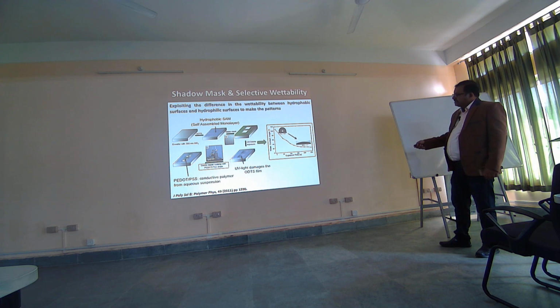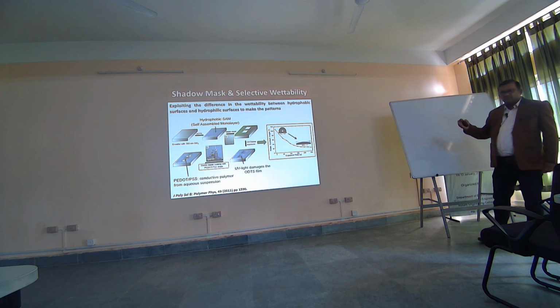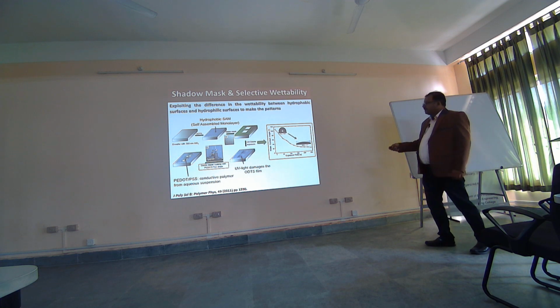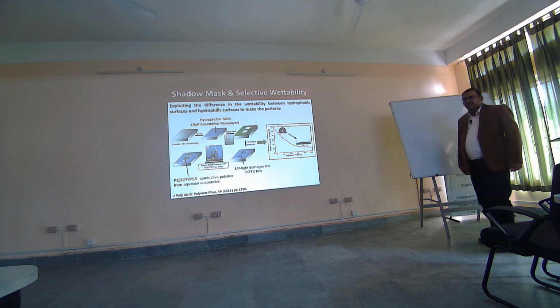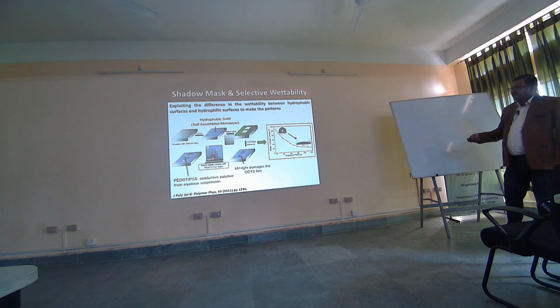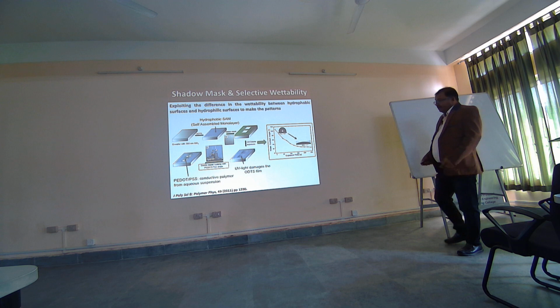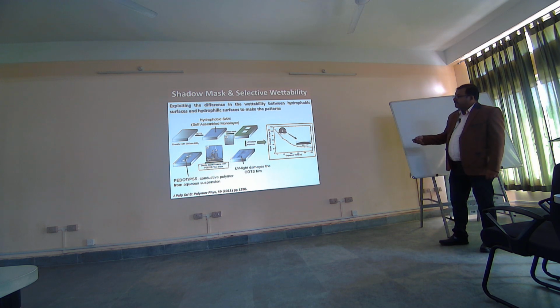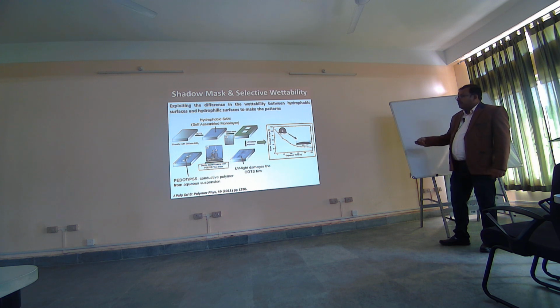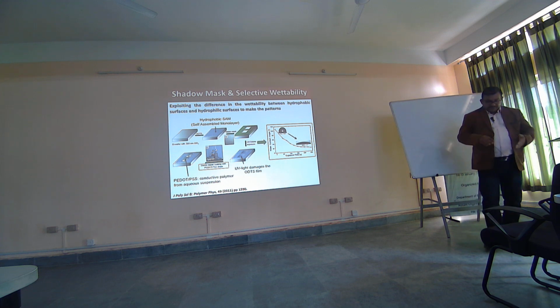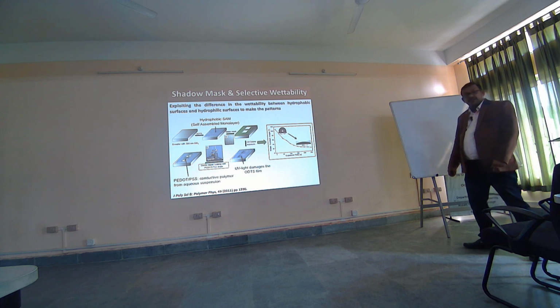Basically, the change in the hydrophobicity is characterized by this water droplet on the substrate. So you see a hydrophobic substrate. Hydrophobic means the water droplet will take more of this kind of shape, because water does not have an affinity to stick to this surface. If your contact angle is close to 90 or even greater than 90, then those surfaces are called hydrophobic. And if your contact angle is below 30 degrees or so, it is typically a hydrophilic substrate. For most of the organic semiconductors that we are going to coat, we would prefer the surface to be hydrophobic and not hydrophilic. So using contact angle measurements, we can see whether the surface energy of my surface is matched with that of the organic semiconductor or not. In case it is not, I can do UV ozone treatment or UV ozone exposure.